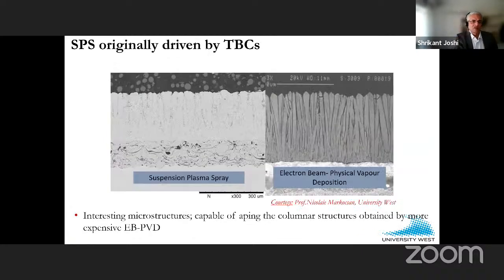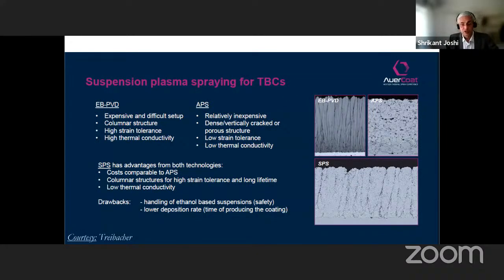So as in case of SPPS, the use of suspensions also was originally driven by thermal barrier coatings. The reason being that very early on, the experimental work revealed that you have a possibility using suspensions to get some sort of a columnar structure, which is not exactly identical to electron beam derived columnar structures, but you get columnar structures which are strain tolerant and therefore bear promise to be used as TBCs, right? So people even now typically compare EBPVD and APS, and suspension kind of lies somewhere in between and has advantages that are handpicked from both of these processes, which are relatively well established.